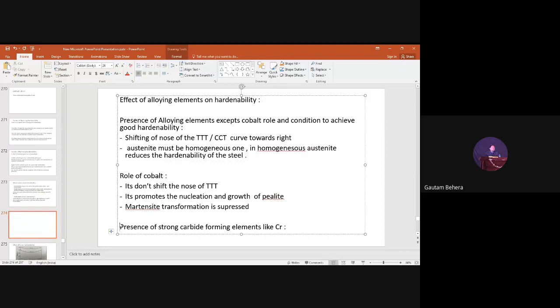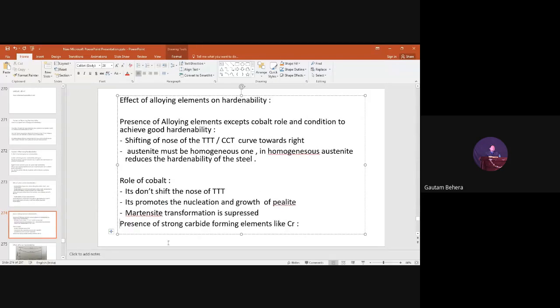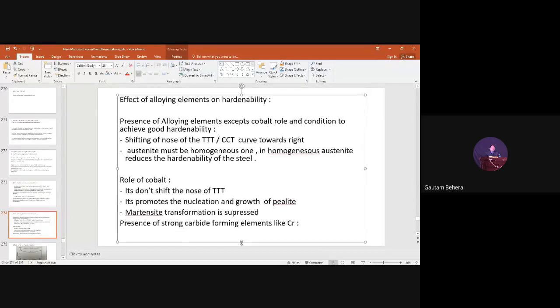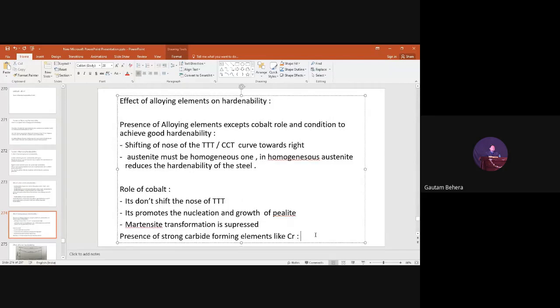Now, the presence of strong carbide forming elements, like chromium. If chromium is there in more and more amount, what will happen? Chromium carbide formation will be there, and the austenite formed will be inhomogeneous basically, because it takes some time to dissolve, or to get homogenized it requires more time, right? You have to go to a high temperature also to make it soluble.